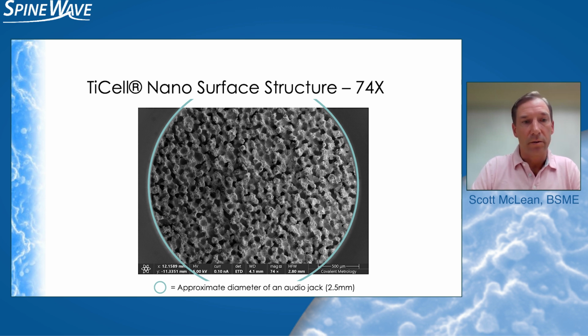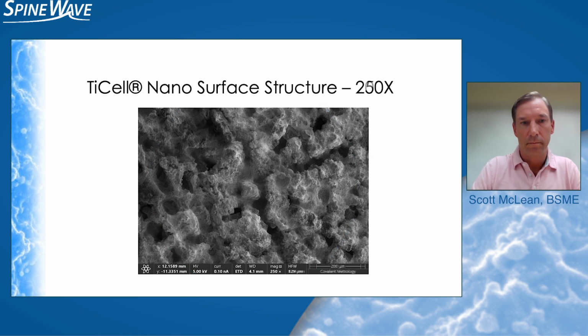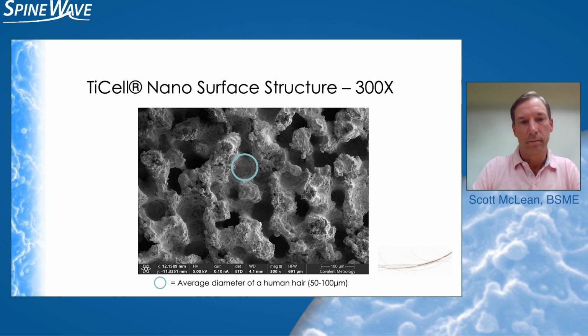And if you look closely, you'll start to see those pits and pores that we were discussing. So I'm going to zoom in right down the barrel of this audio jack. Now we've reached a magnification of 300x, and now we can clearly see the pitted and pore structure of the surface. And you'll notice we have a circle drawn on here. This circle is 75 microns, which is similar to the diameter of an average human hair. And as you look at the pits and pores, again, you can see that they are of a similar size to that circle, indicating that we are in the range of the size of osteoclastic pits with these pits and pores.